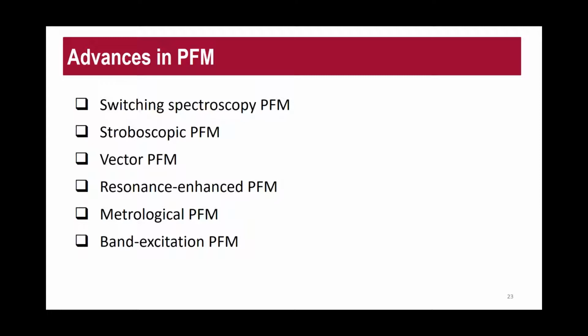So you need to provide these external sources to excite your material so that it can be captured by the PFM. It's important for you to understand your material before you measure under PFM, so that you won't later comment, how come I wasn't able to obtain information from PFM. So first of all, you need to understand your material before using PFM. This is a very important message. And also, the tip selection is important, because not only the conductive tip, but the type of conductive layer is also a key criterion in how it will respond to the charges, because it is all about the resolution, the sensitivity, and your expectation of this imaging tool.